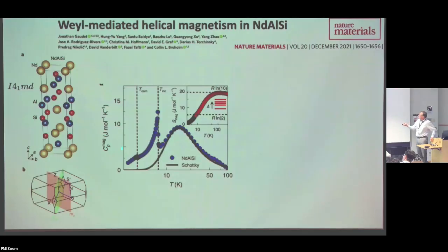The reason that it tends to happen like this is because the RKKY interaction is a long-range interaction, so it typically produces, you could say, a spin density in the system that likes to oscillate with a certain wavelength, which is associated with nesting conditions on the Fermi surface. And as you throw in the F electrons, they enforce that and eventually end up having this kind of modulation in real space. And so it's quite normal to get this structure.